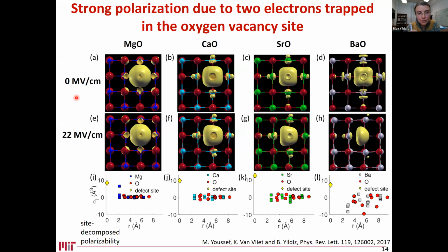And the source of the polarization in the system, even though these oxides in their bulk nominal are not polarizable, they are not polarizable oxides, but the source in this case becomes predominantly the defect itself. So if you look at the charge density distribution under zero field and under about 20 megavolt per centimeter, we can see from the charge density distribution that primarily the polarization is arising because of the trapped electrons at the oxygen vacancy site. And there's a small contribution from the surrounding sites as well, but quantitatively the dominant contribution is from the trapped electrons.